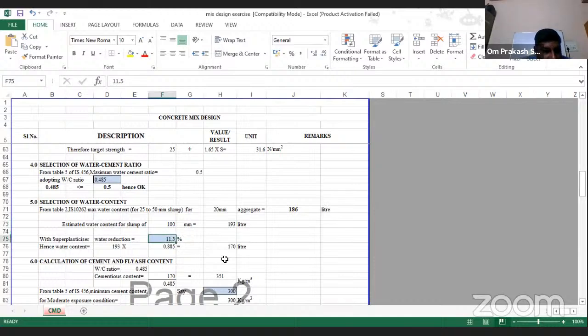Now, we are using a super plasticizer. So we are assuming that by using this super plasticizer, we'll reduce the water content by 11.5%. Okay, let's not use the super plasticizer. We are not using any super plasticizer in the mix, so I make it 0. So what will be my water content? 193. If I am using the super plasticizer and I assume that, let's say, water demand will reduce by 10%, my water content reduces by about 20 kg. See again, friends, I am not using the super plasticizer. I am making it 0. The water content is 193.